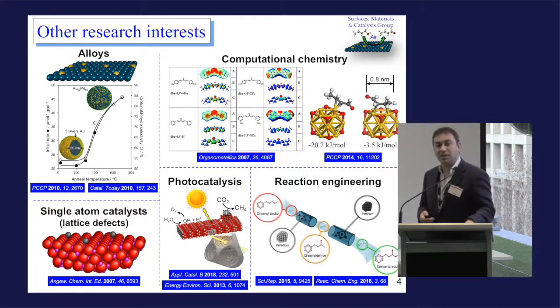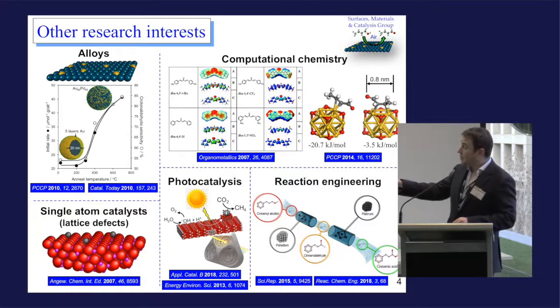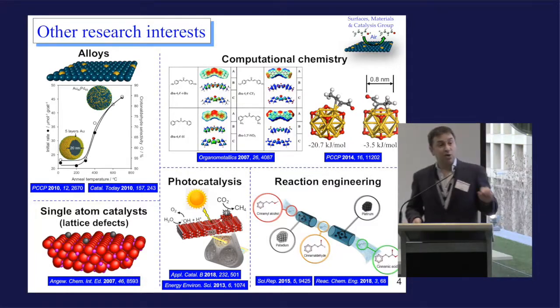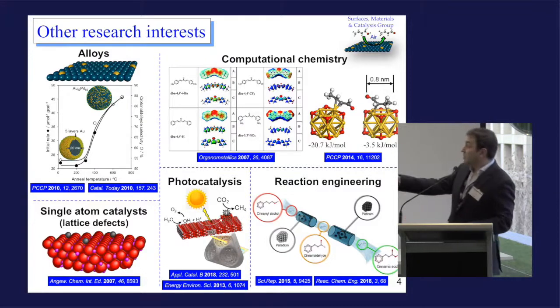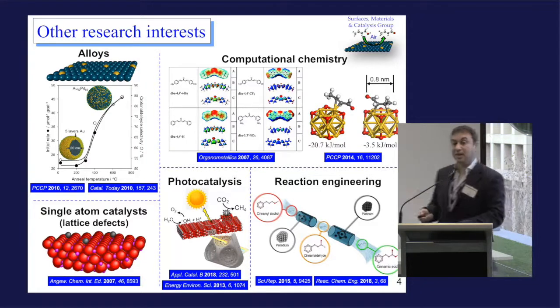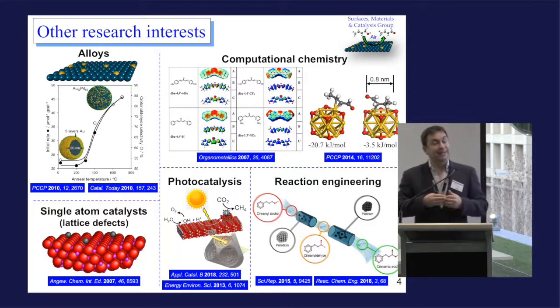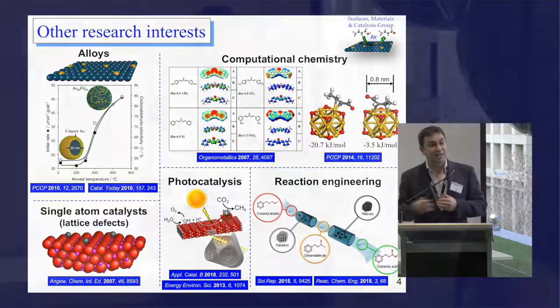the formation of defects and the roles they play in catalysis, and particularly the role that they play in pinning individual atoms. So there's a huge amount of interest in trying to move towards more earth-abundant catalysts by, for example, reducing the precious metal content that goes in traditional industrial processes. So it's called precious metal thrifting, traditionally. So here we've been able to take a single palladium atom, by pinning it at defects in an oxide lattice, we can actually dramatically enhance the activity of each of those atoms. And so that allows you to bring costs down dramatically and get better control over selectivity. That's been done. Thank you.